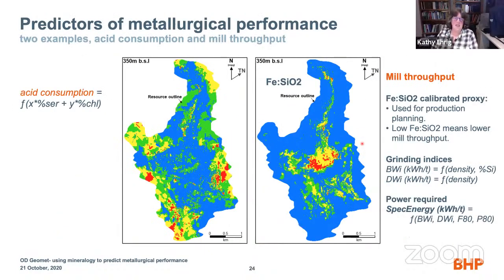We even go down one more set and look at just two of our predictors of metallurgical performance. And these are examples of acid consumption, which is a big concern in tails leach, and simple things like mill throughput. Acid consumption is expressed simply as a function of the weight percent of siderite, not sericite, the weight percent of siderite times a function of the weight percent of chlorite in the ore. So that just means a function of the weight percents of the acid soluble minerals. Pretty obvious. And we see that acid consumption is high in parts of the deposit. These edges are not necessarily high copper bearing areas, but we can look at those. This is an example here of where using a proxy works out pretty well.